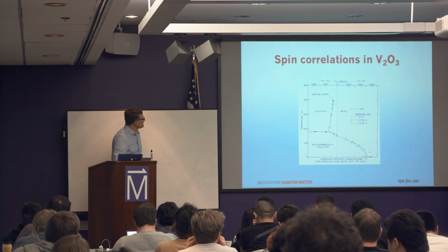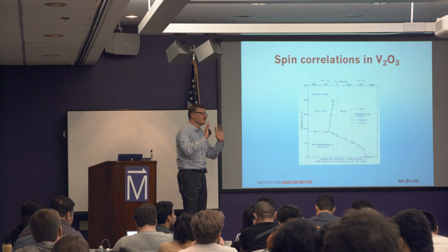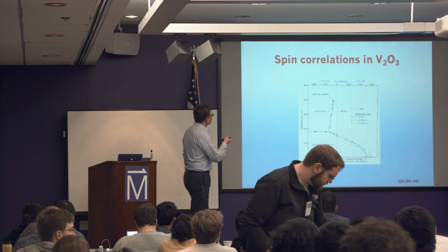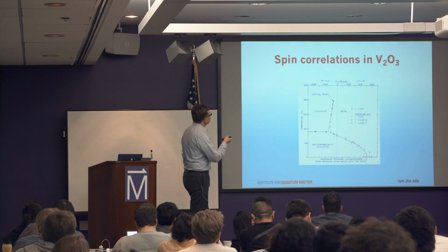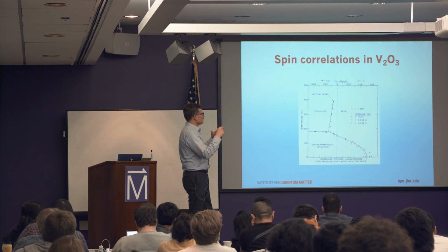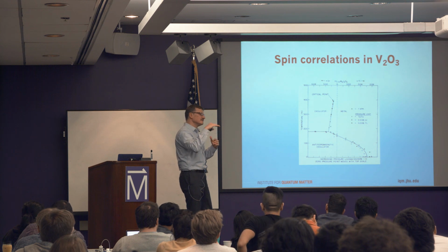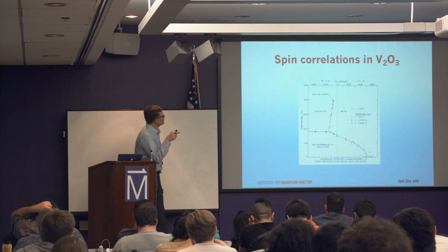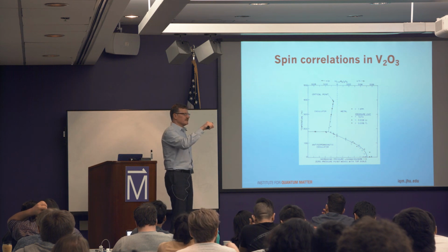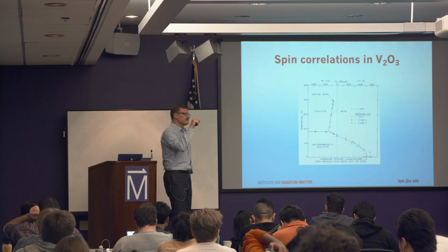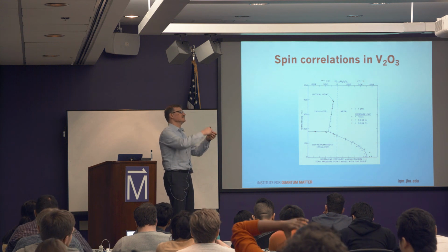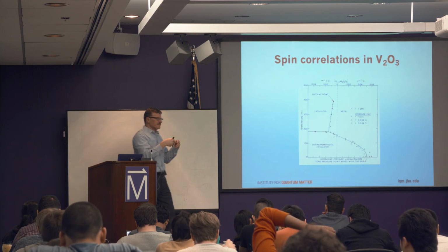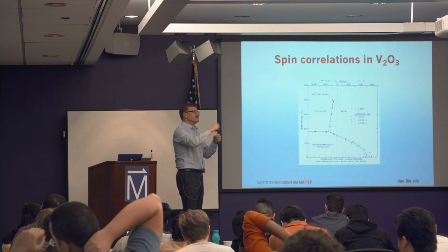Basically, the simplified description is as follows: chromium has 3 3D electrons, and so that tends to produce a half-filled shell in the particular point group symmetry that we have here. So it becomes a site in your lattice which is difficult for an electron to hop to, because you have a big gap to the next state that could go in there. Whereas titanium is the other way around. It is a site where it's easier to hop to.